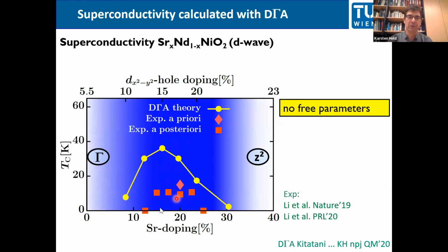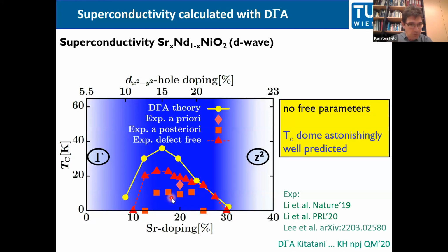Many people jumped onto saying here you have D wave and then you have P wave, in particular for multi-orbital calculation. That was some outcome of their calculation. But it even gets better because the very same group as the previous data point shown here has more recent data, which are now defect-free. So there's an agreement both of the range of doping, of the amplitude of TC, and of the skewness of the curve, in very good agreement with the theoretical prediction. So in cuprates, we have a symmetric dome, but in the nickelates, it's skewed to the right-hand side because of this nonlinear doping dependence.